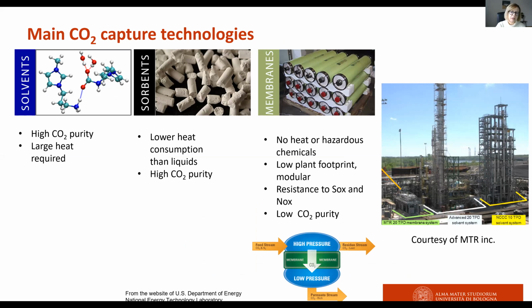The membranes, compared to the most established solvent and sorbent technologies, are different in the fact that the membrane is a continuous process. The membrane does not require regeneration. It does not require heat. And also, membranes are normally resistant to the most aggressive contaminants present in flue gas or in other gaseous streams containing CO2. And the main disadvantage of membranes is that you can achieve a lower CO2 purity with this technology compared, for instance, to solvent absorption.